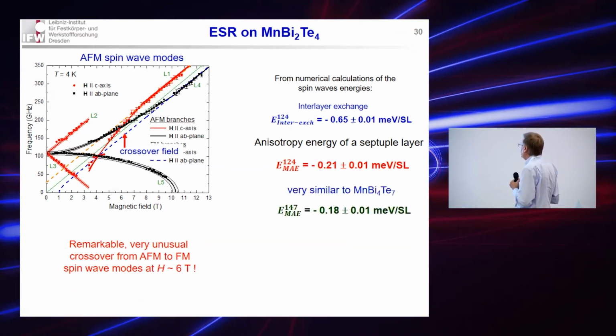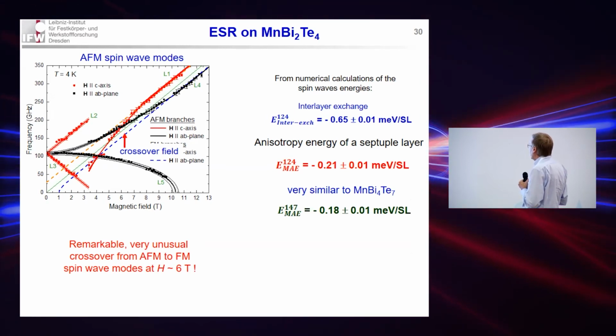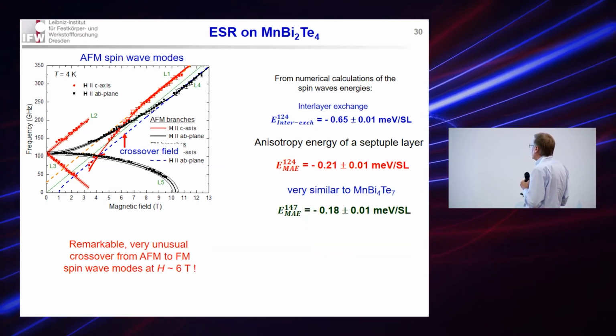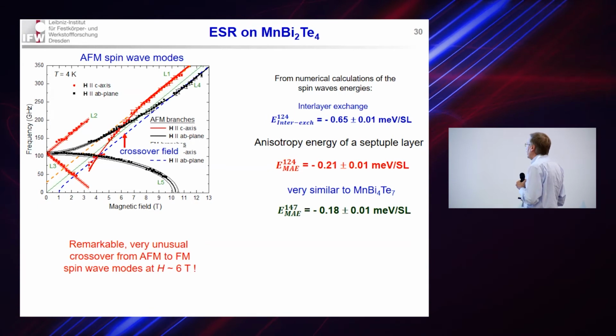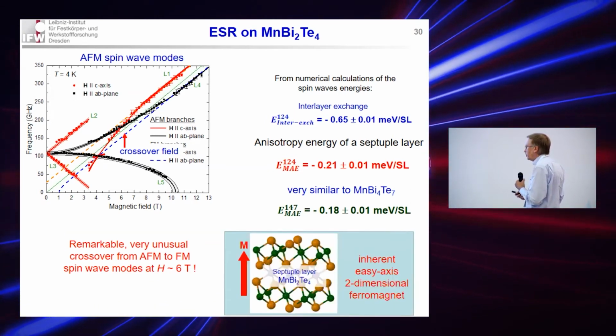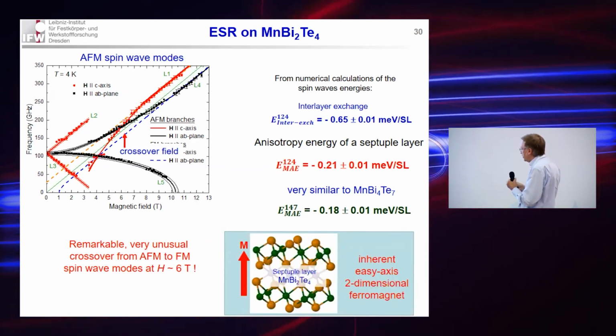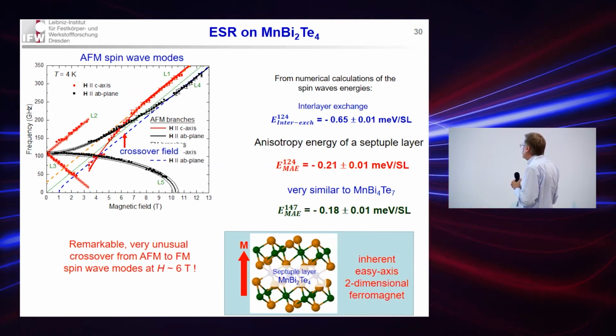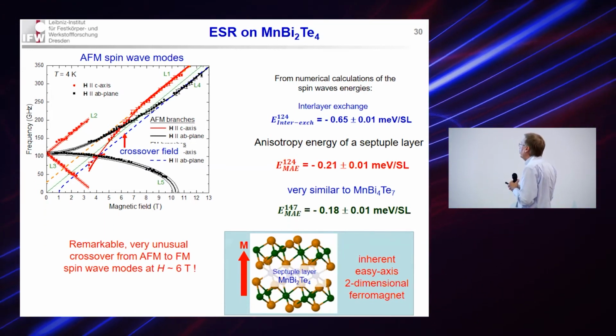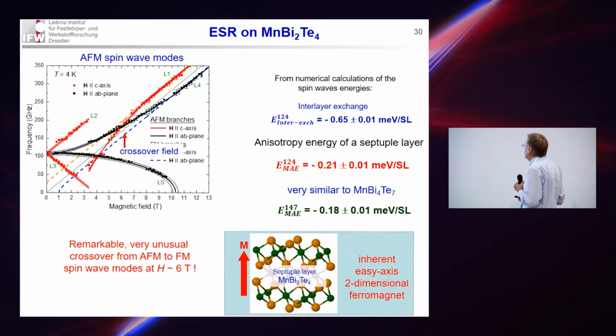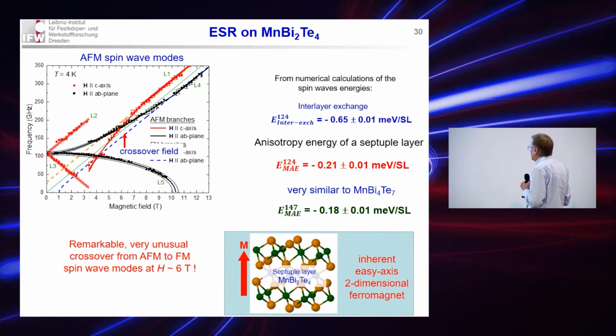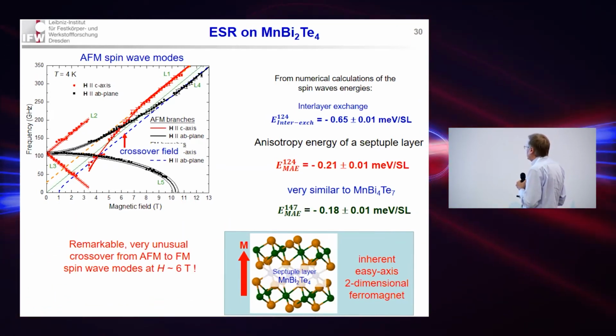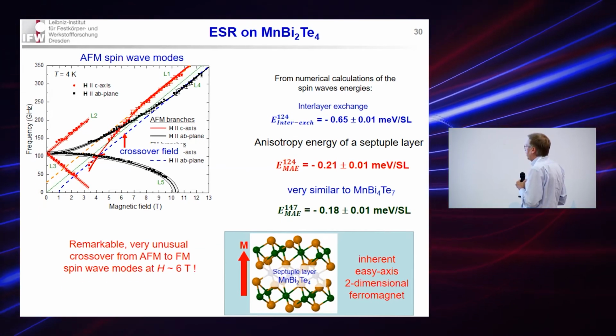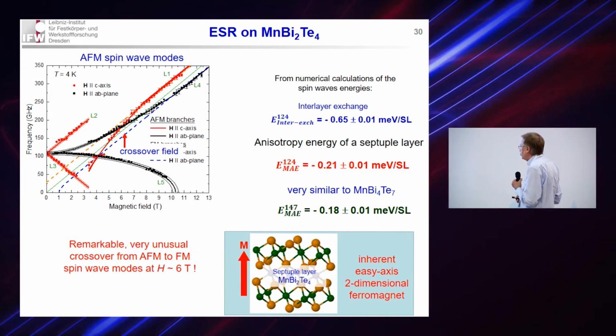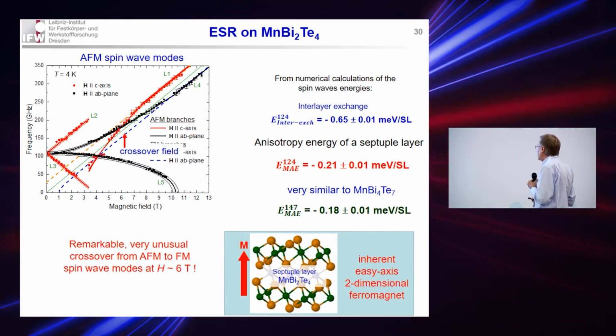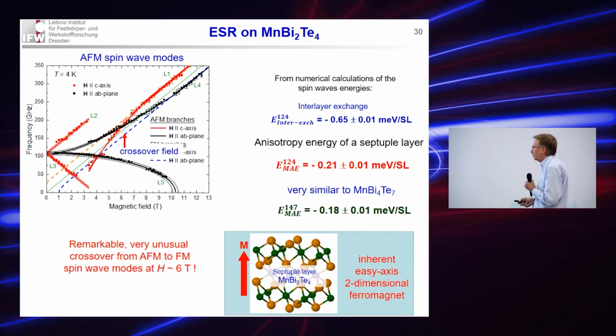And now let's compare it with the result of the 1-4-7 compound. There we obtained very similar values, although the structure is different. So this comparative study of 1-4-7 and 1-2-4 suggests that the magnetic units of this family of magnetic topological insulators are inherently easy-axis two-dimensional ferromagnets.